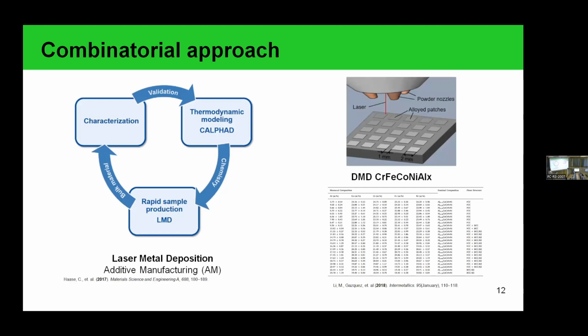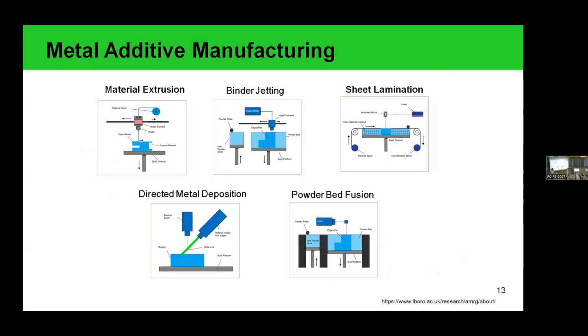There was a work in which a batch of samples was presented. There they varied the aluminum content in each sample and first analyzed the phase composition of these samples and also the mechanical characteristics. So today there are several metal additive manufacturing techniques. Material extrusion and binder jetting involve printing solid parts using polymers, but they require an additional heat treatment procedure afterwards to remove this polymer from the solid parts. In sheet lamination, we apply a laser or heat source to the sheet of material, and with vibration we weld our sheets of metal.